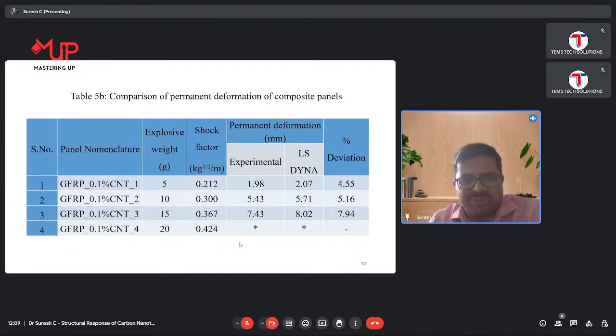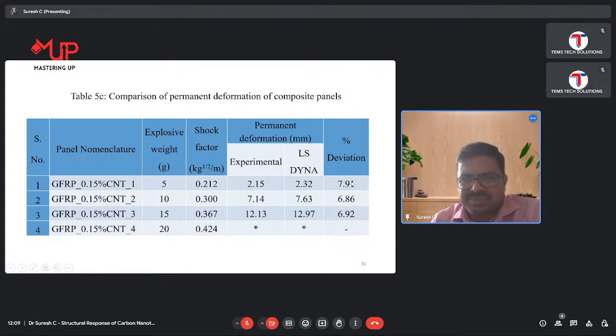This is for 0.1 weight percentage of CNT, how the damage has taken place and what is the deviation. So when we go for 0.1, the deviation has reduced compared to neat composites. And this is for 0.15, how the deformation is taking place. Here also the deviation is reduced, and it comes close to 6.